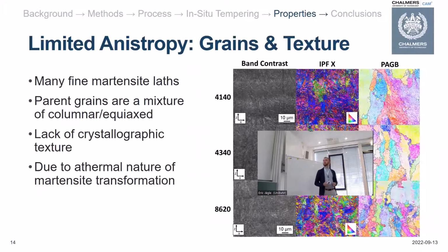I think I'm running slowly on time, but the last point I want to bring up is I mentioned before you have lower levels of anisotropy when you're comparing. So the difference between vertical and horizontal specimens was only about 5 to 8%. And that primarily is due to the martensitic transformation itself.